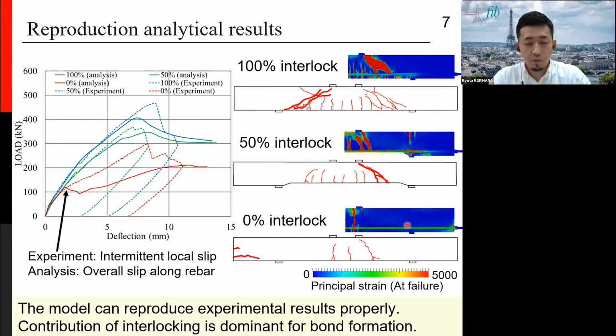In contrast, in the experiment, the rebar slip was a very local and dynamic phenomenon, and the slip and stop were repeated locally. So dynamic analysis should improve the accuracy in the 0% case, but the other cases with interlocking by the solid model were reproduced well. So the bond model, reproducing the chemical and the friction factor, has room for improvement, but the interlock by the solid model has high validity. So it means that the contribution of interlocking is dominant among the three components of bond.